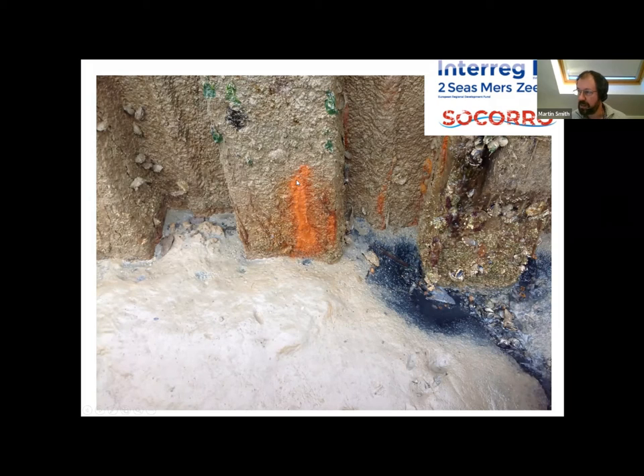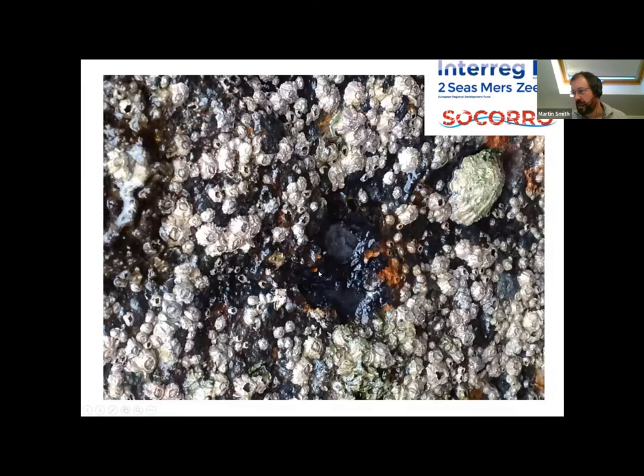These are purely simple visual evidence of this phenomenon called accelerated low water corrosion. If we chip one of these away, under that structure, we can actually see acid etched steelwork. So this is not oxide in there, that is clean steel. So what is going on inside those blisters is generating acidity, and that is enhancing the corrosion rate, and it's directly acid etching the steel. So that's what we want to understand.